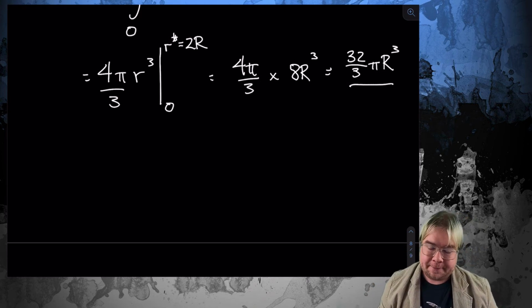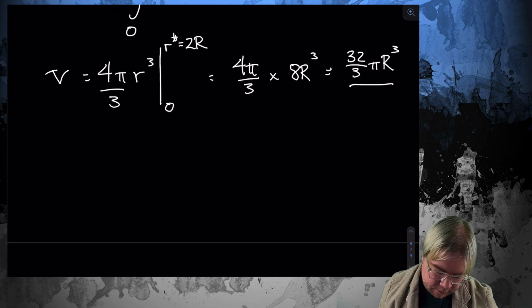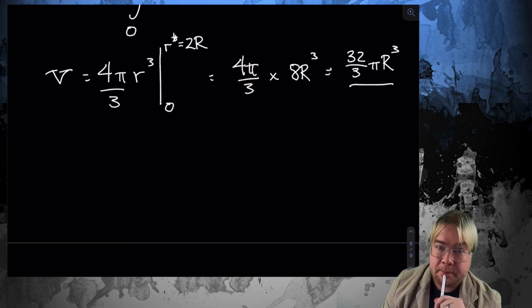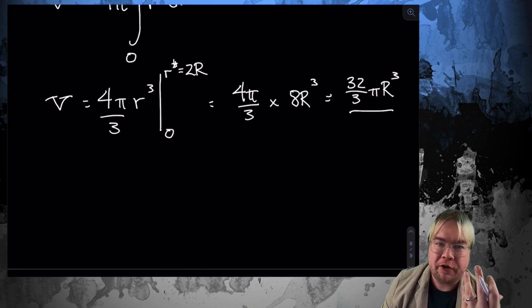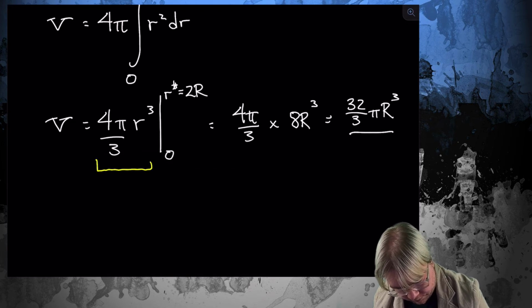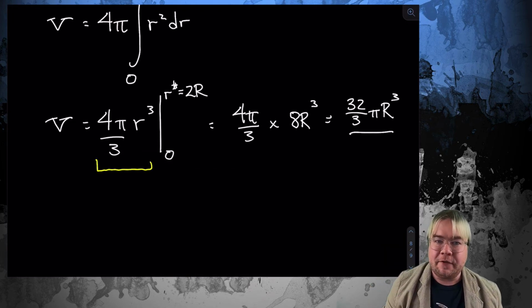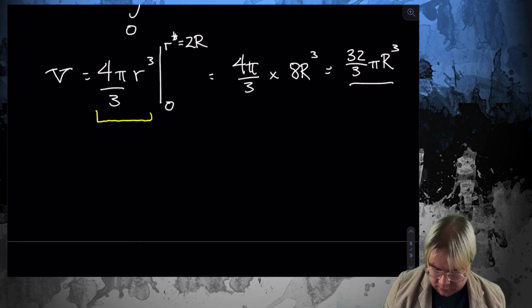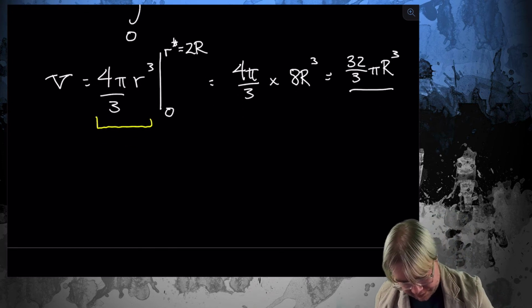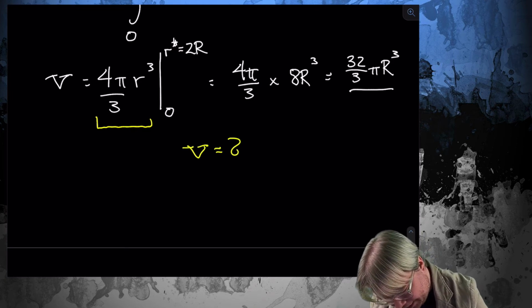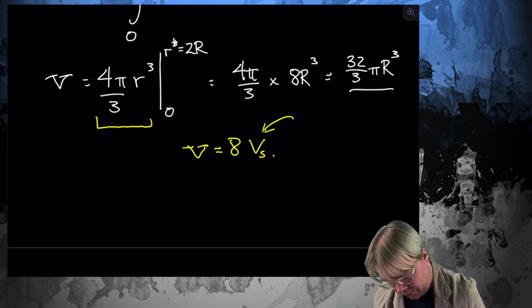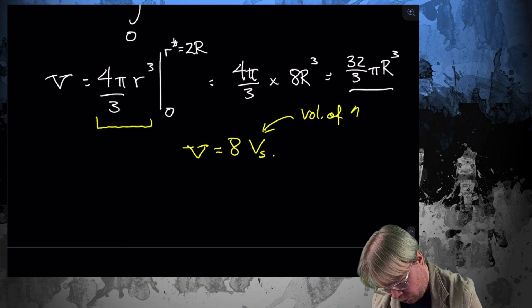So this is good in a couple ways. One, this shows you how to calculate the excluded volume. Two, when we did this expression, we got a volume, right? I mean, if you look at this term right here, that is the volume of a sphere. So this gave us a volume. That's great. The only other thing to notice here is that the excluded volume that we calculated was 8 times the volume of the particles. So Vs is the volume of one sphere.